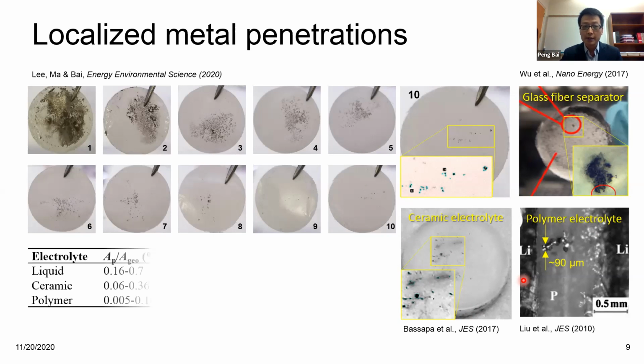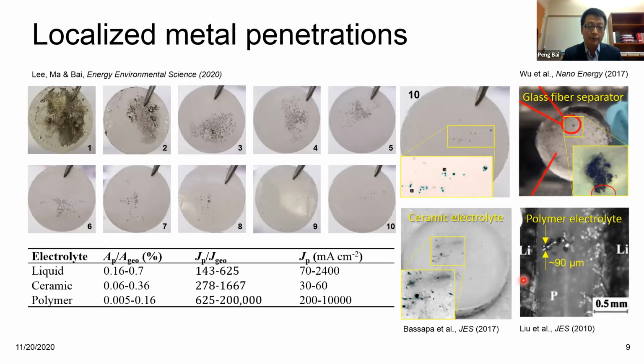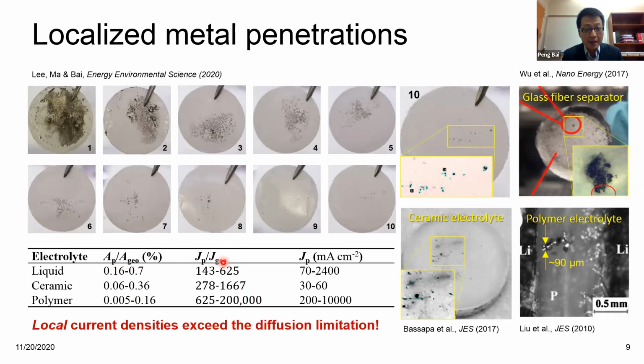happen locally. So then if you quantify the areas, you can see that the penetration area versus the geometric area is very, very small. That means you have a very large amplification factor or current focusing effect here. And when that happens, the local current density easily exceeds the diffusion limitation. That means if you calculate by using your electrode area, okay, that's safely designed. It's a current density that will never reach the diffusion limitation.